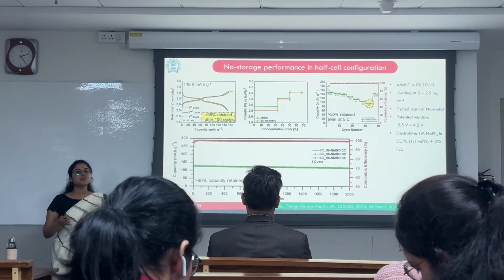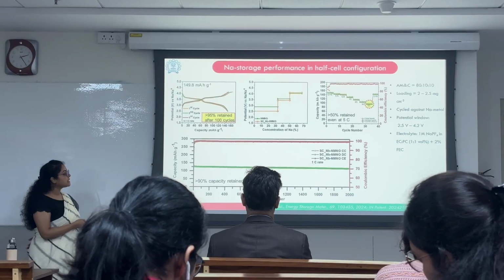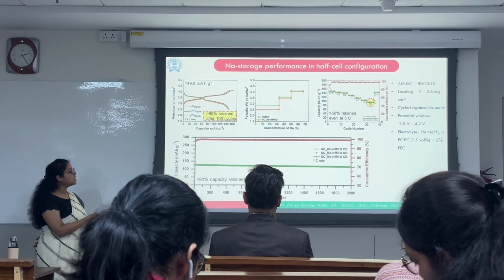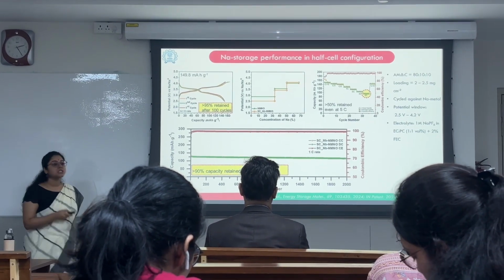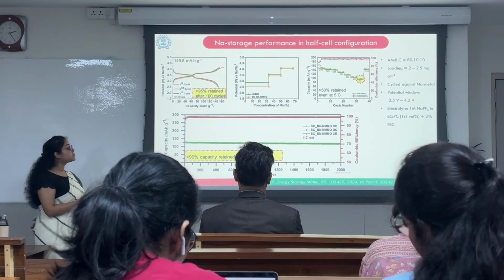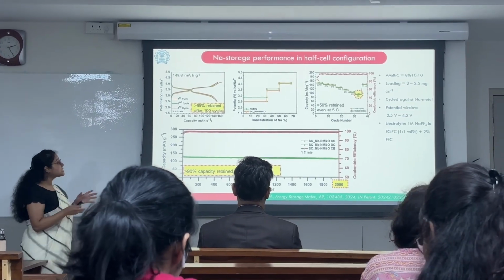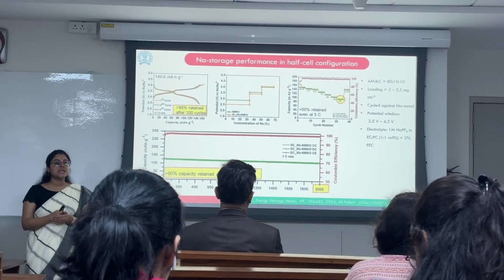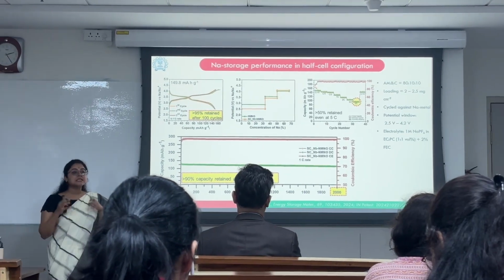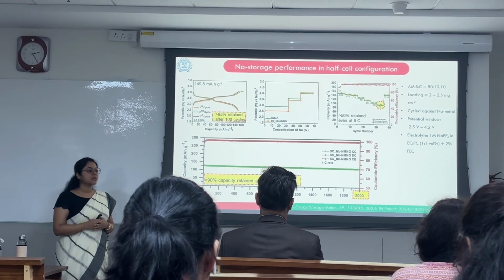Now, that is the reason why we tested the long cycle life at a higher C rate of 1C, which shows that it gave us a capacity of more than 90% after 2000 cycles. So this suggests that the niobium doped NMNO cathode has been successful in suppressing the phase transition.